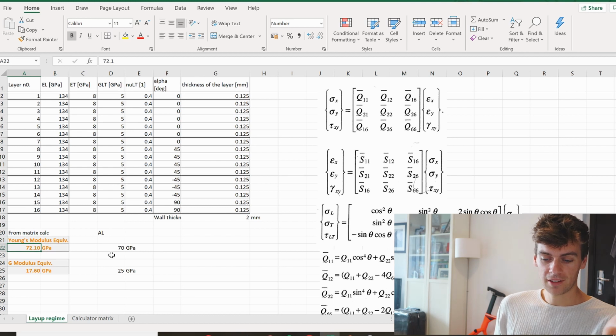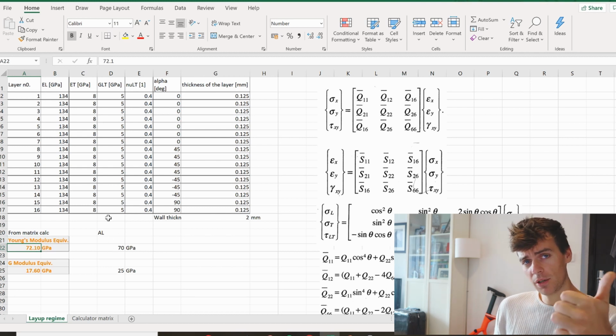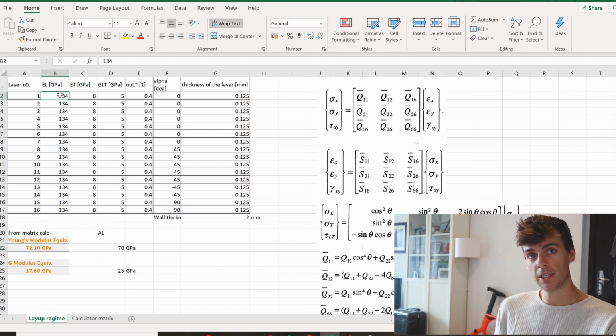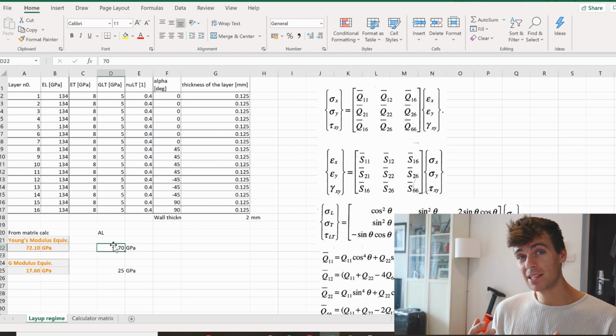Now, that is crazy, because we started at 230 gigapascals for the fibre, then we got to 134 for a single UD ply, and now we're down at 72 gigapascals for the whole shape. Let's remind ourselves that aluminium is 70. So by doing this layup, half the fibres at 0 degrees, around half of them in torsion at 45, we've massively reduced the stiffness of what we thought we had, and now we're down at 72, which is basically the same as aluminium.